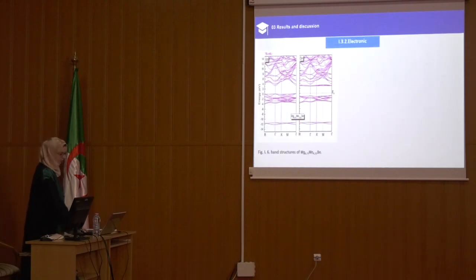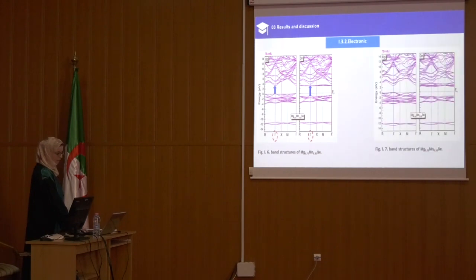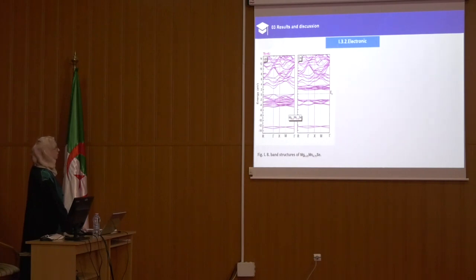For the electronic properties, both spin orientations up and down with concentration equal to 0.25 and 0.5, we have a ferromagnetic semiconductor, where the maximum of the valence band is situated at the gamma point of the Brillouin zone, which preserves the semiconducting character in these alloys. Same observation for MgSe doped with manganese at 0.75 concentration.